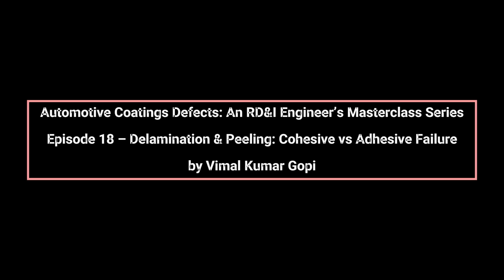High glass transition temperature systems, excessive bake severity, or improperly balanced resin-hardener ratios can create films that are strong but unable to absorb mechanical or thermal stress. Under impact, thermal cycling, or humidity expansion, these films crack internally and peel even though adhesion to the substrate remains intact. Film build plays a critical role in both failure modes.